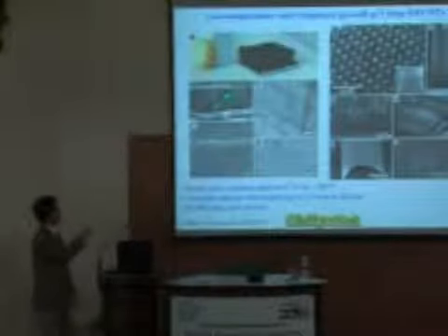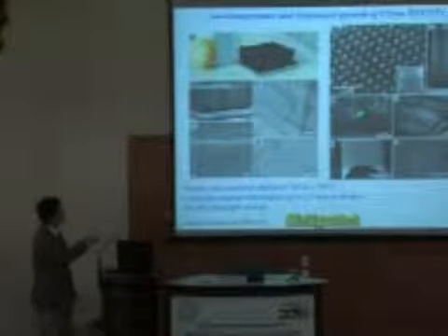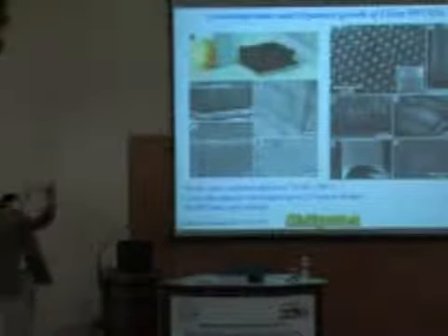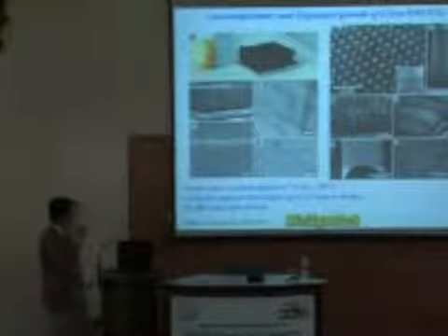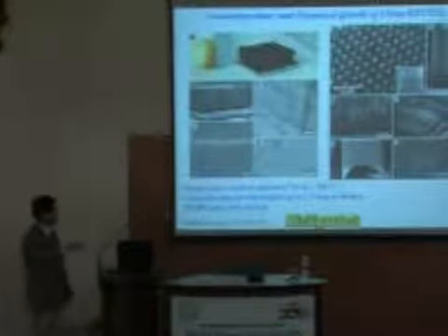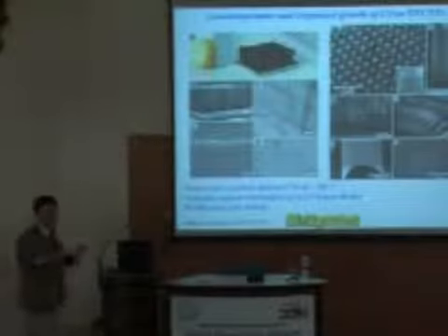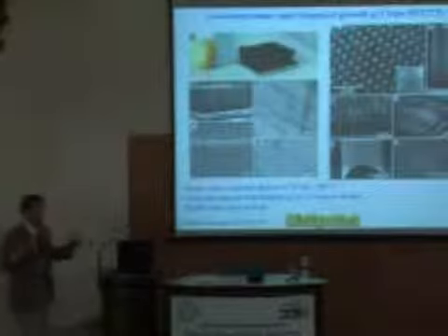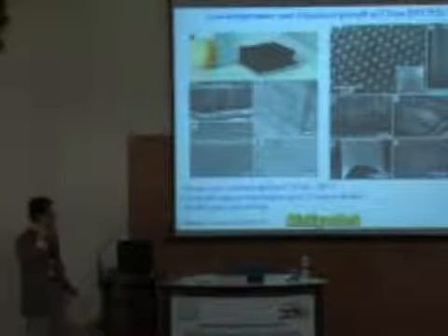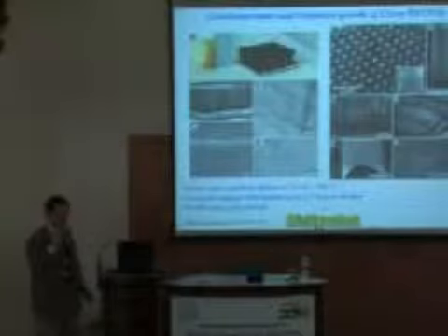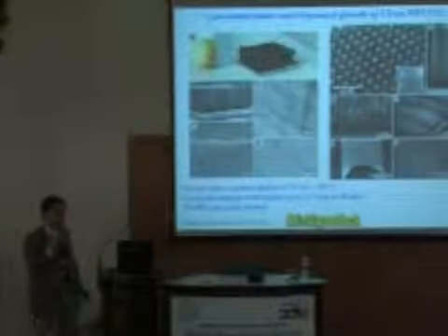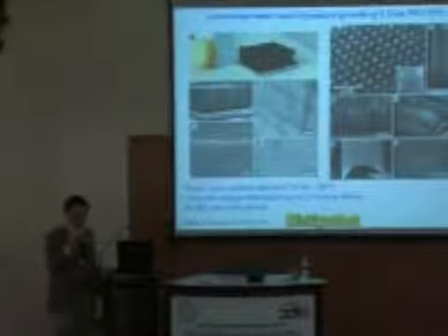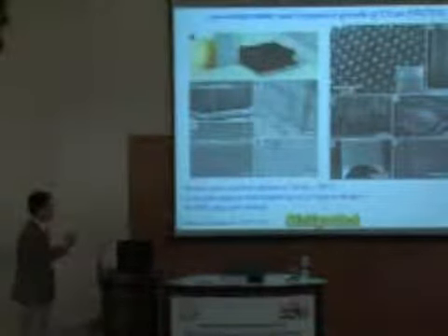And you can see, if you zoom in here, the tubes look like this. A whole bundle of the tubes are actually clumped together and become a pillar, right? And this is very important work in the sense that they are using water to clean up the catalyst and clean up some of the amorphous carbon so that the tube is nice, clean, and pure. However, if you think carefully, if you are using water to clean the amorphous carbon, it means you have the chance that you will oxidize your carbon nanotubes at the same time. So you will create defects in your tubes. So this is very exciting work, but it's not the best.